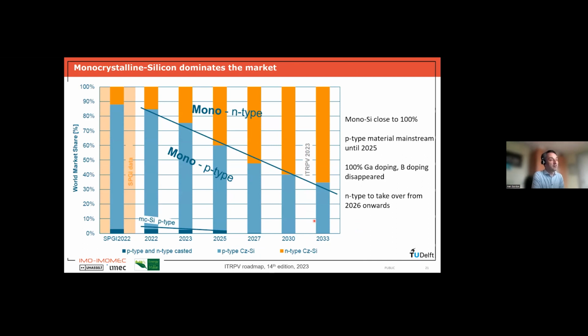Then a second thing which is very important to note is that at this moment, almost the whole production of silicon photovoltaics is using monocrystalline silicon wafers. So until, let's say, 5 years ago, I think the majority of the solar cells made were based on multicrystalline silicon. And the reason was that multicrystalline silicon wafers were a lot cheaper than monocrystalline silicon wafers. And although the efficiency that you can achieve with multicrystalline silicon was lower, it was still competitive.